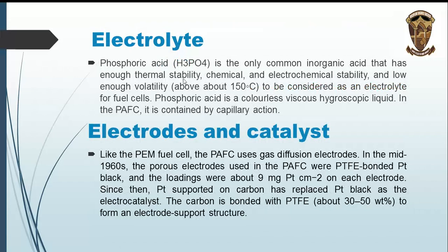Phosphoric acid (H3PO4) is the only common inorganic acid with enough thermal, chemical, and electrochemical stability and low enough volatility above about 150 degrees Celsius to be considered as an electrolyte for fuel cells. Phosphoric acid is a colorless, viscous, hygroscopic liquid. In the phosphoric acid fuel cell, it is contained by capillary action in the electrodes and catalysts.